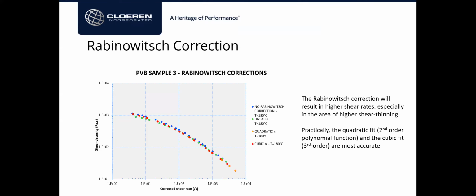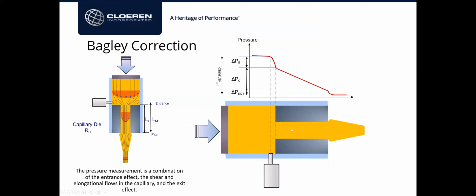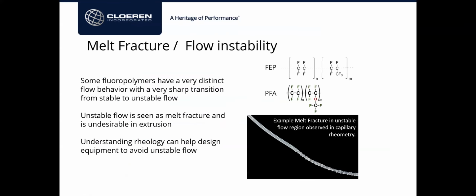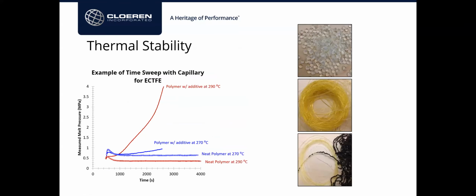Okay. Can you please comment on the degradation experiment and thermal stability with additive in regards to molecular structure? Just curious why the pressure increases. Yes, that's a good point. We see degradation going both ways. So what I mean here is that in general, the viscosity is changing or the pressure is changing over time. In this particular case, I don't know what the additive was, but the result seems like it did increase the viscosity quite a bit, and basically the material was burning, right? Almost like this picture here.